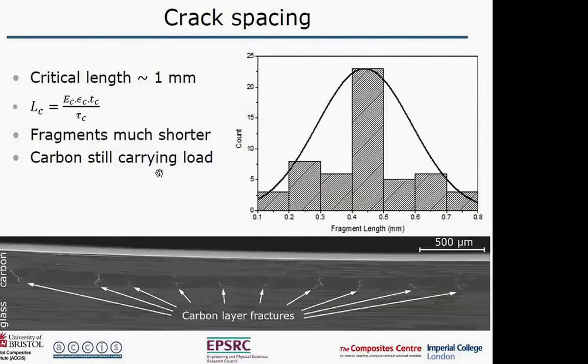What that tells you is that these fragments do not affect the load carrying. It's still carbon, it's still carrying load, and therefore it's able to fragment further. It's not like it's completely unloaded here. You've got to load it up by shear to get enough load in to break it again. It's still carrying load and therefore can break at the next weak point along the ply where the critical failure mechanism can start. So the carbon can still carry load.